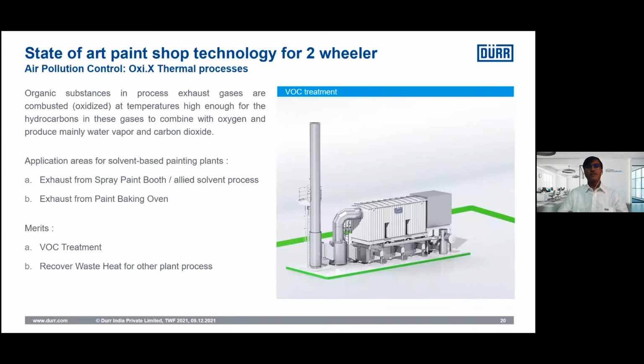Next is the VOC treatment system for solvent exhaust from the spray booths and allied exhaust of paint bake ovens. Solvent-borne oversprayed paint is scrubbed in the spray booth, while the solvent exhaust stream in dilute phase can be concentrated and fed to the thermal oxidizers for VOC treatment before it is released into the atmosphere, thereby complying with environmental regulations such as CO less than 100 milligram per Nm3, NOx less than 400 milligram per Nm3, TOC, that is total organic compound, less than 20 milligram per Nm3, and SPM less than 50 milligram per Nm3.